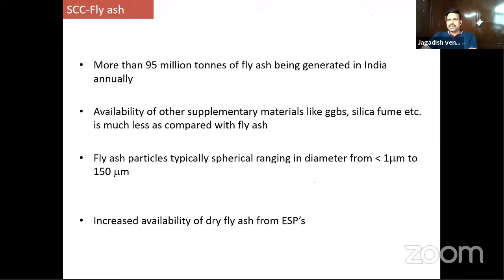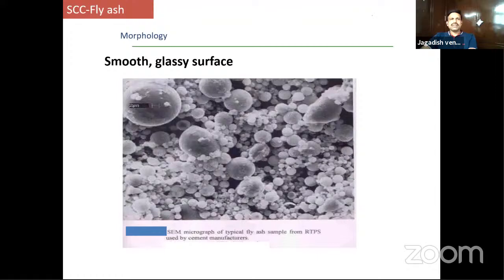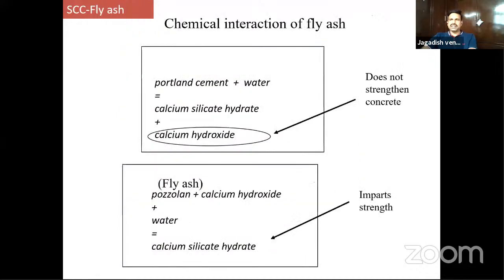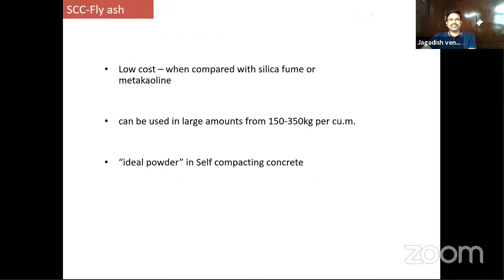And when you look into the particle nature, these particles are typically spherical, and the diameter ranges from less than 1 micrometer to 150 micrometers. And we have more availability of dry fly ash from ESPs, that is electrostatic precipitators. This is how the morphology looks, the smooth, glassy nature. That's how you get the ball bearing effect in the concrete, particularly in the fresh properties. This I have already explained. When you add any supplementary cementitious material, secondary reaction happens, and that's how you get more CSH gels, and it imparts strength to the concrete.